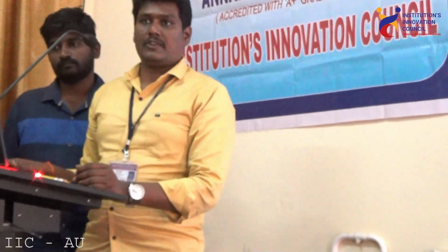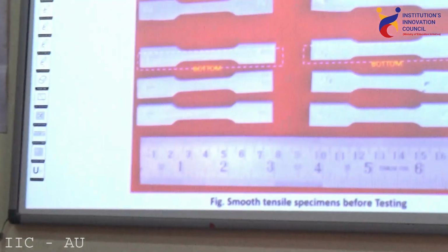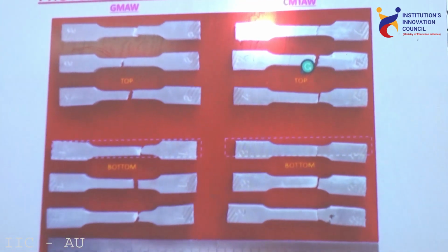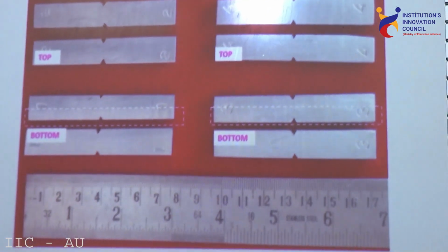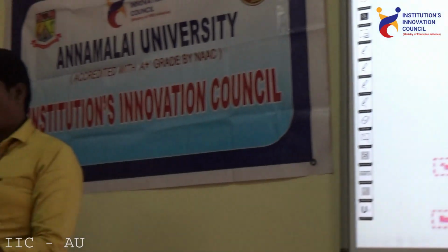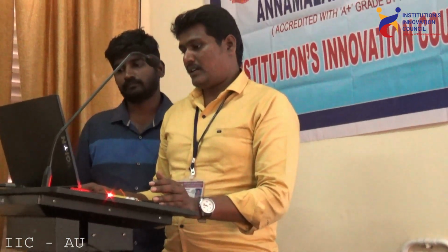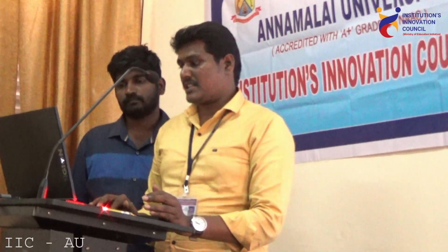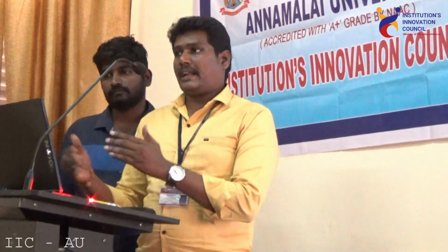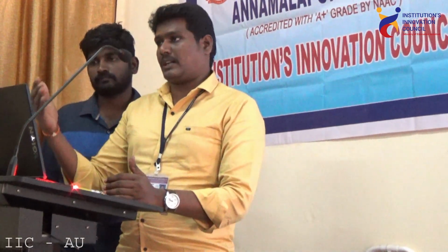And this is the photograph of smooth and notch tensile specimens, and these are the tested specimens before and after testing. These are the notch tensile specimens and the tested specimens. These are the impact specimens, and these are the images of the tested samples. All the testing was carried out according to ASTM standards. In the GMAW process, visually we can see some nodules and a rough surface, but in the CMT process we cannot see that, because the process is very smooth and clean.